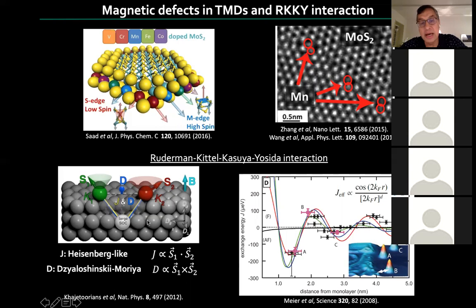that has electrons. And as an electron scatters from one of these magnetic impurities, it carries information on where the impurity is and what its spin is. And as it carries that, it scatters with a second magnetic impurity and conveys that information, right? The probabilities for scattering, if you will. And so it turns out that if you ask what is the net effect of this various scattering from the electrons, it can be described by this RKKY interaction by a Hamiltonian.